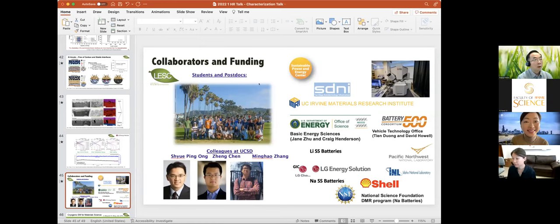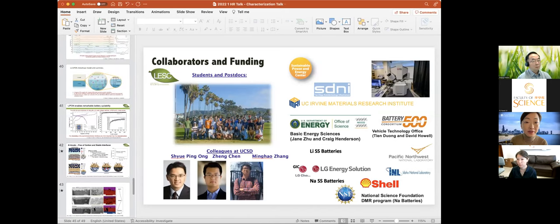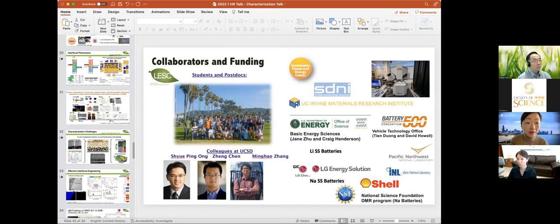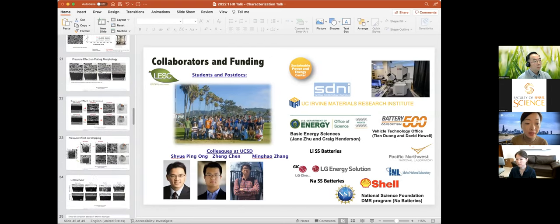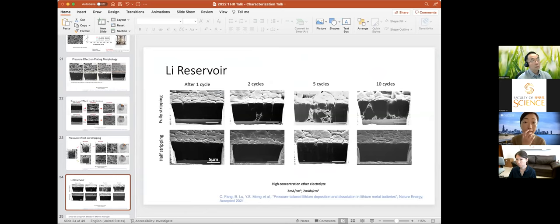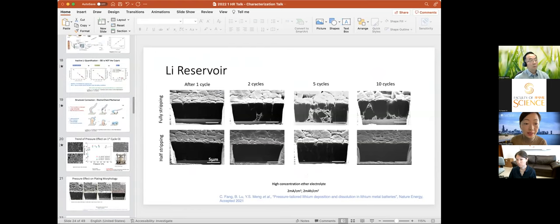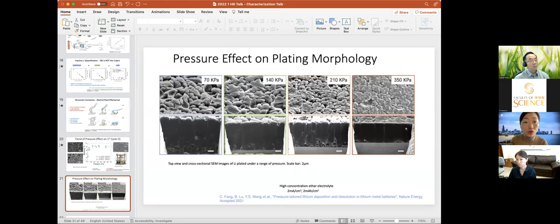Hi, Shirley. I have a very short technical question for the samples showing the lithium metal cross sections. Are these samples all cut by FIB? Yes, all the samples have to be cut by cryo-FIB, right? Because if you do it at room temperature, the contamination is very severe. You can see in our lithium metal these columnar vertical grains, and those grains will disappear if you overuse room temperature cutting.